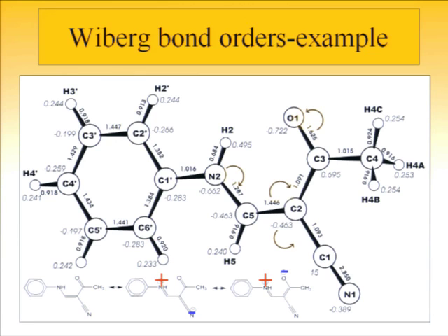It means that here some electron clouds were distributed from and to bonds. Again, the same happened here, where one would expect double bonds, but the bond order is only 1.6, so it means that the electrons from the bonds were pumped to the oxygen atom. If you wish, you can see that the bond orders around this ring, which is aromatic, are all around 1.4, which is quite a good estimate. The same holds for CH bonds here, so that this ring is pretty stable, and there's actually no surprise.